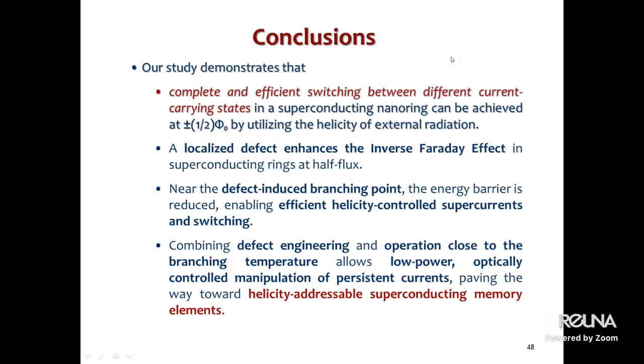But on the other side, what we thought originally, that the defect is antagonistic to the effect, finally led to the conclusion that it's not the case if we are below the branching point, but the opposite. It preserves the switching effect, and even decreases the switching time, let's say the response time for the switching effect.